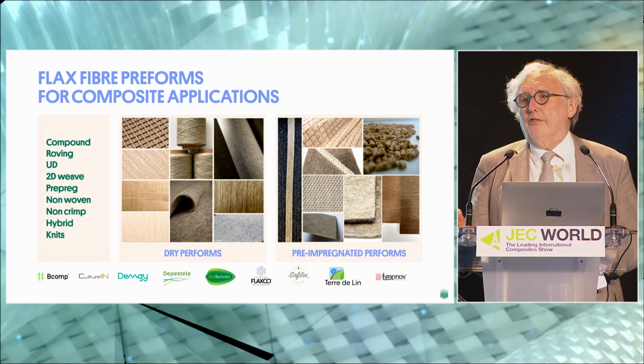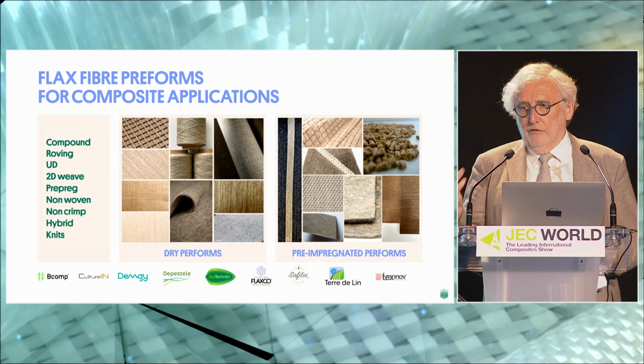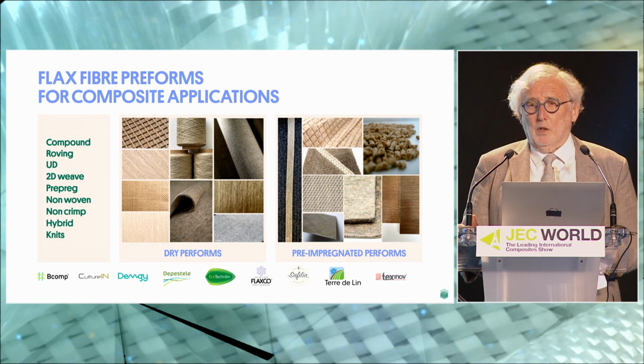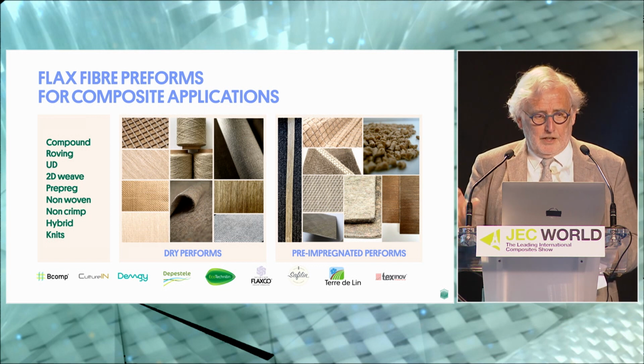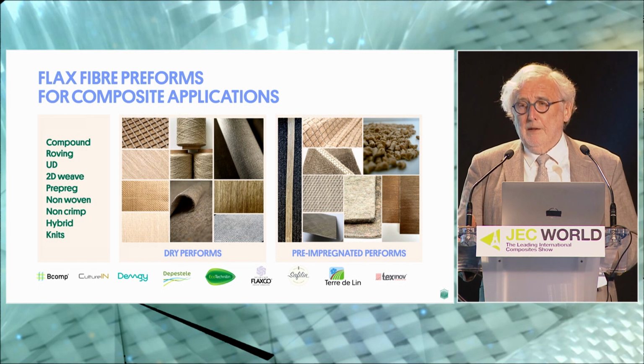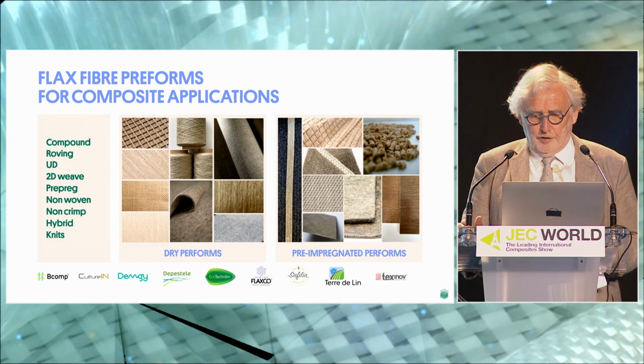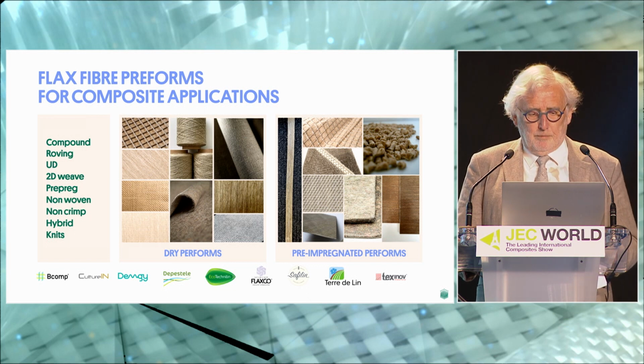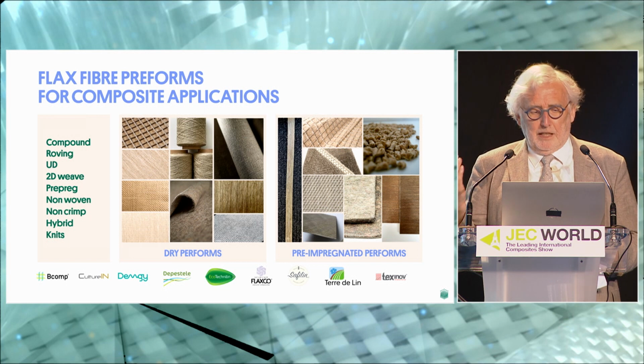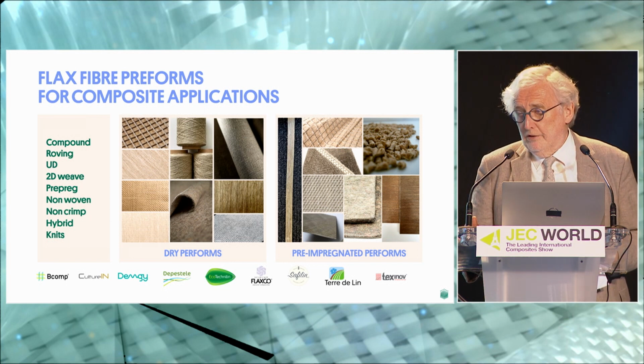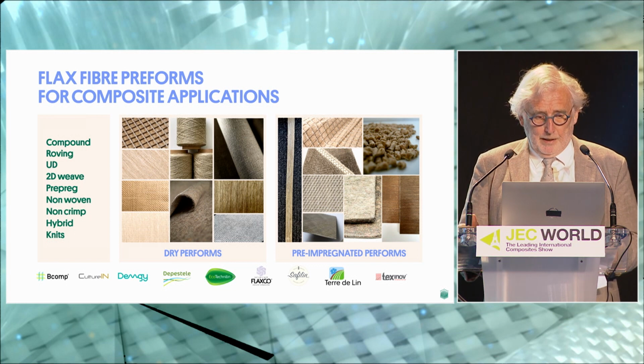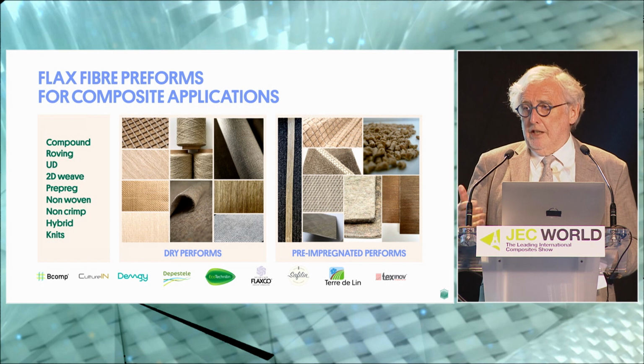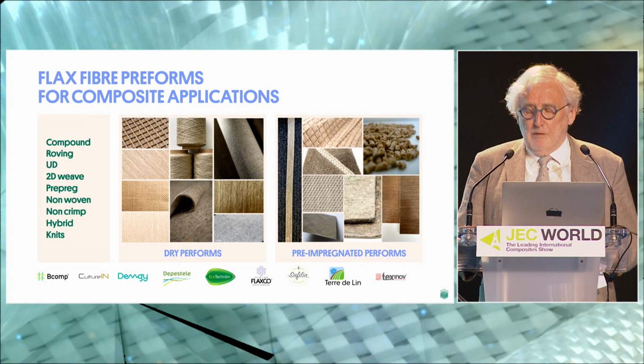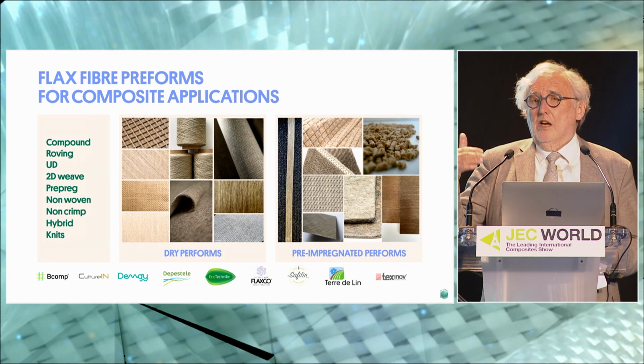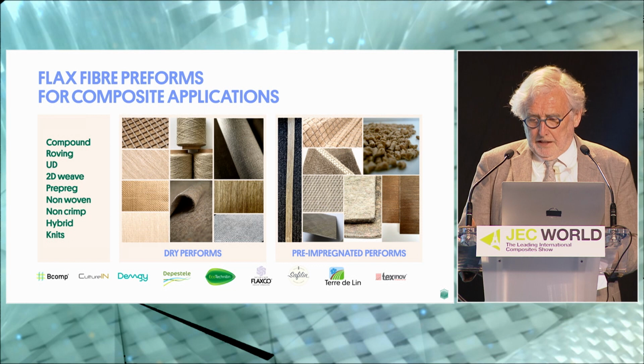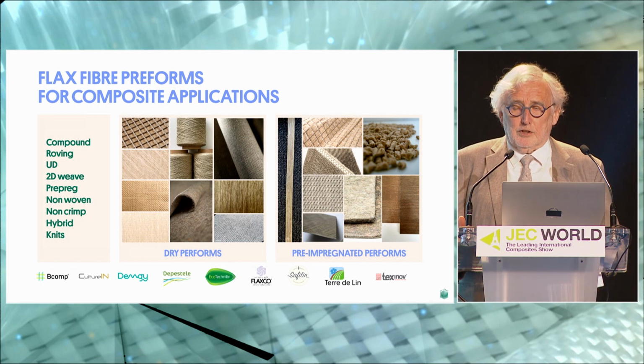So we have short fiber compounds for injection molding, for SMC and BMC. We have unidirectional rovings, we have unidirectional tapes, we have two-dimensional weaves, these are dry preforms to the left. To the right you see pre-impregnated preforms, prepregs, UD prepregs, woven prepregs. We have non-woven materials, both dry and in prepreg form. We have non-crimp fabrics, uniaxial but also multi-axial non-crimp fabrics. We have hybrid materials where, for instance, carbon and flax are combined, and even we can produce knits if we need special formability